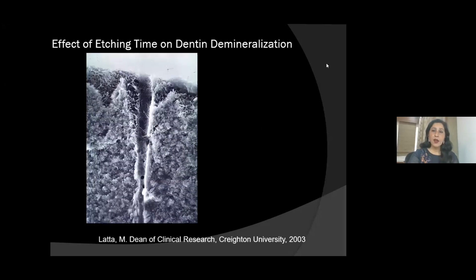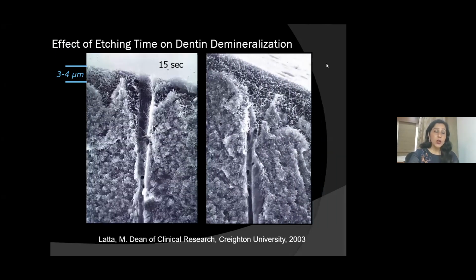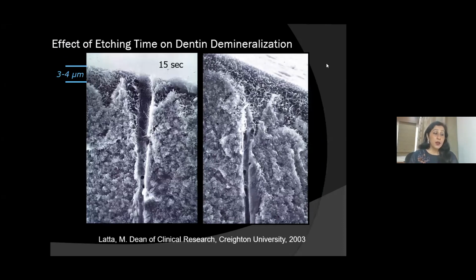So for my friends who are using total etch technique, this is a special tip for them. How to etch. So friends, the recent advancement for enamel etching time is 15 seconds. Do not etch the enamel more than 15 seconds. And for dentine also it is 15 seconds. Previously we were taught, and there is still a controversy, but the most recent studies advocate that when you etch dentine for 15 seconds, the dentine demineralizes to 4 micrometers. And the bonding agent also just fills this 3 to 4 micrometers only.